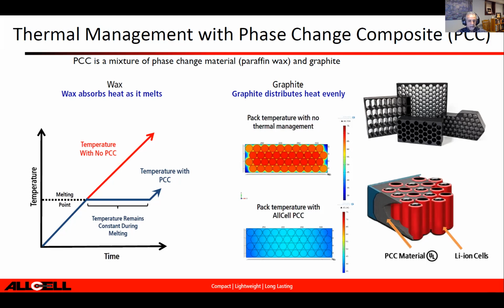As you can see, the beauty of this is that by moving the heat around, if you don't have a system to do that, like the graph in the middle, the hot cylinders, these are the cells without phase change composite. You can see that the temperature exceeds the safety limit, and the temperature gradient across the module is significant, which in most cases leads to degraded performance and degraded cycle life. However, in the one at the bottom middle, you see that with the phase change composite, you spread the heat with the graphite, and then the wax absorbs the heat at the preset temperature, and you end up achieving the thermal management criteria that you're looking for.